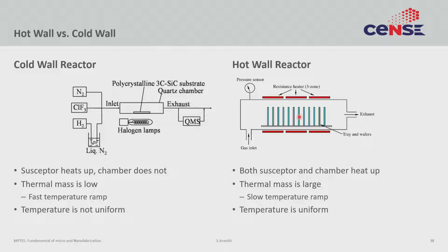As long as the substrate is insulated from the chamber, the chamber remains cold. Compare that to a hot wall reactor, where the whole thing is enclosed in a furnace with resistance heaters in contact with the quartz tube. The quartz tube heats up, which in turn heats the gases inside, which in turn heats the wafers. So in the cold wall case the chamber remains cold; in the hot wall case the chamber remains hot.